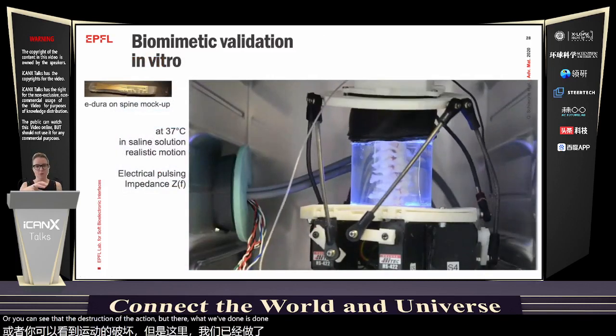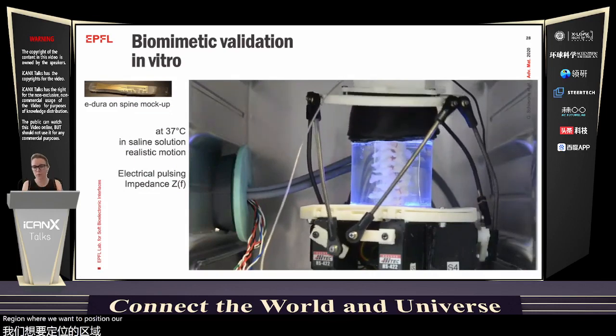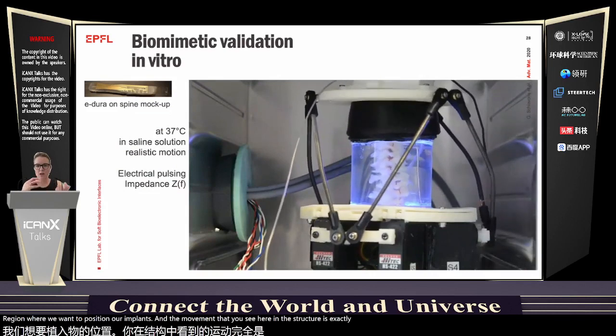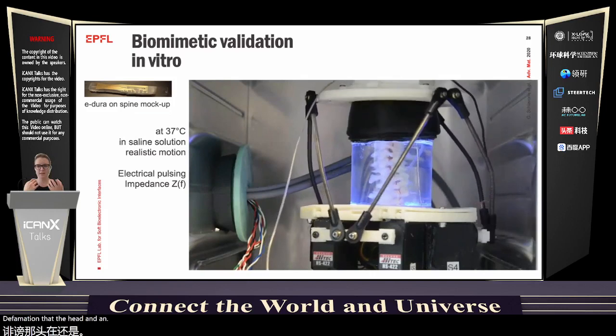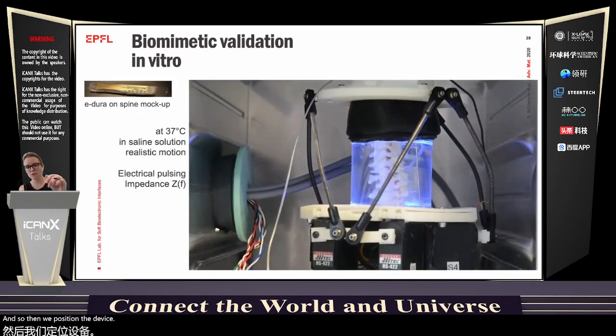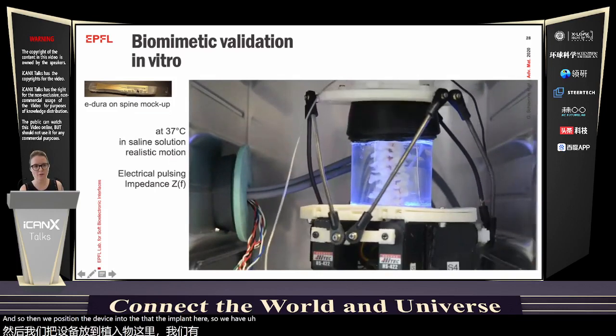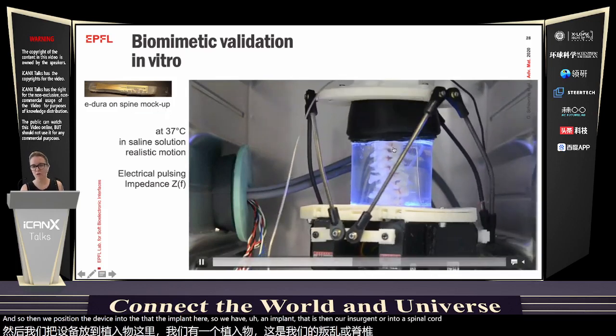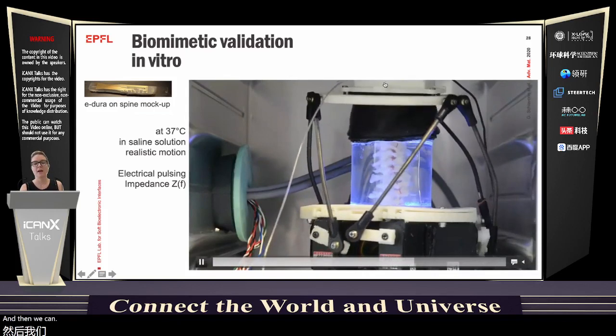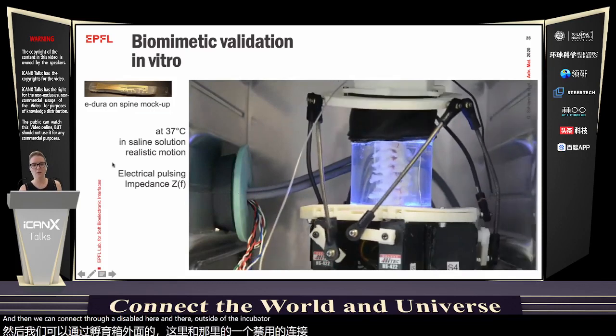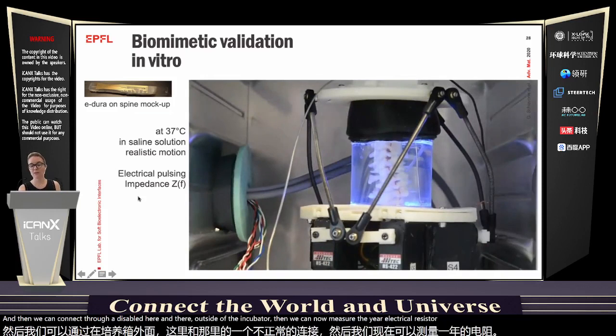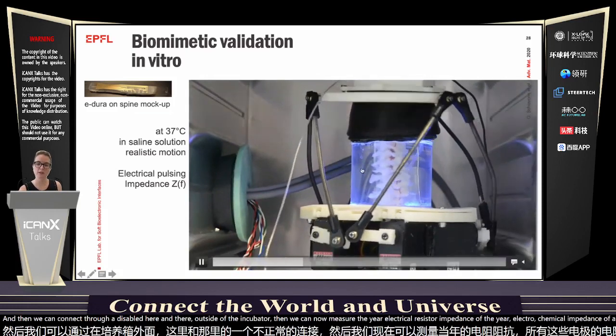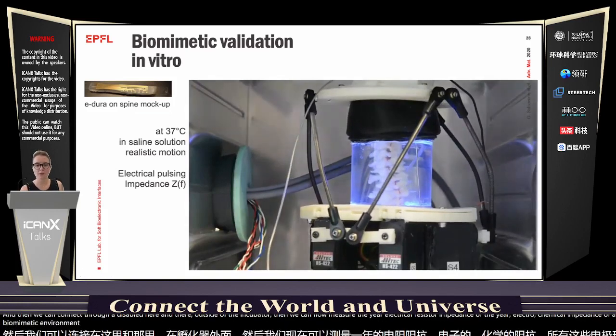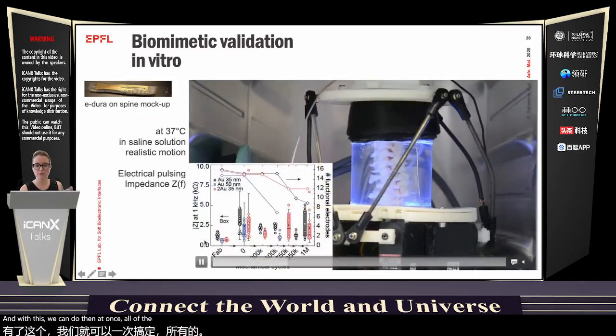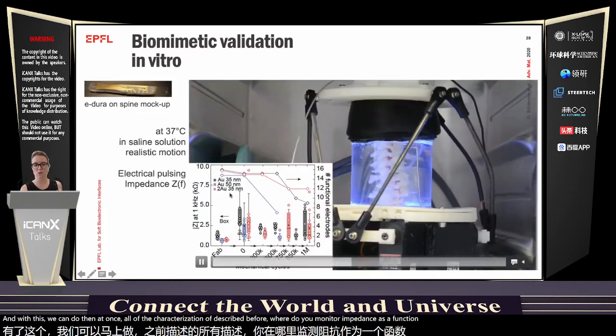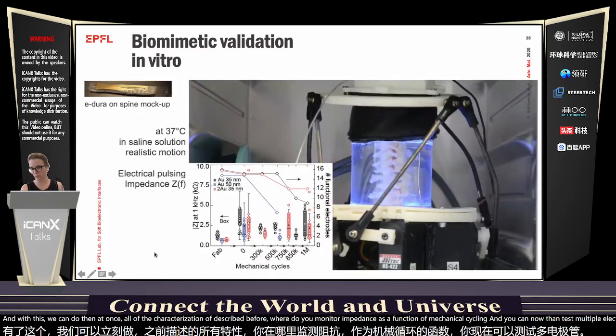There, what we've done is replicate the cervical region where we want to position our implant. The movement that you see here in the structure is exactly the replica of the type of deformation that the head or the neck would do when you move your head. And so then we position the device into the implant here. So we have an implant that is inserted into a spinal cord mockup that sits in those 3D printed vertebrae. And then we can connect through this cable and outside of the incubator, we can measure the electrochemical impedance of all of these electrodes that are now sitting in a very realistic biomimetic environment. And with this, we can do at once all of the characterization I've described before, where you monitor impedance as a function of mechanical cycling, and you can now test multiple electrode technologies or interconnect technologies.